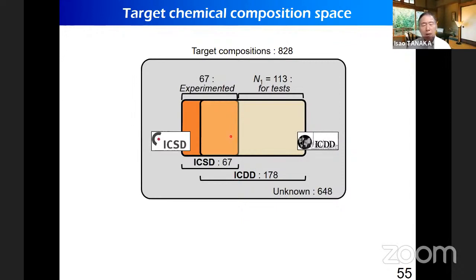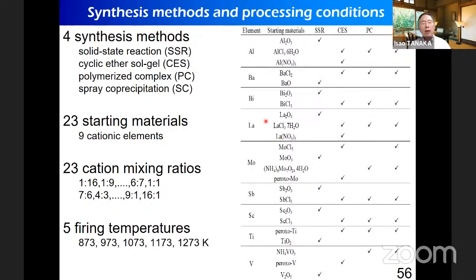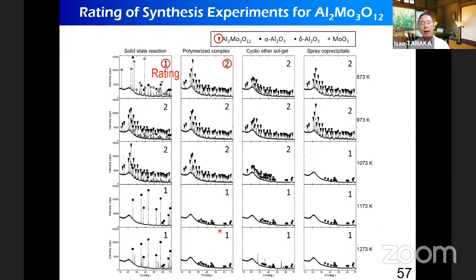So we use this orange part as a training set to examine whether we can successfully predict the processing conditions of this ICDD compound. For the synthesis, we have chosen 4 different synthesis methods, 23 starting materials, 23 cation mixing ratios, and 5 different firing temperatures. For the characterization, we have made X-ray diffraction. For this particular compound, under this particular condition, we succeeded in synthesizing this compound by X-ray. And for this synthesis method, we failed to obtain the target material.